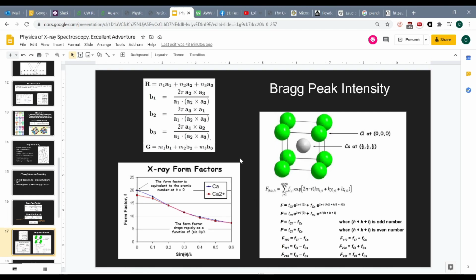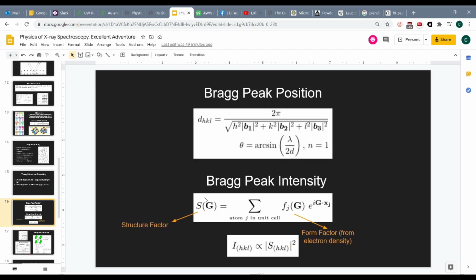Okay, so a little bit more about the Bragg peak intensity. The X-ray form factor can be calculated either experimentally, or you can do some rather involved derivations involving the electron density, and you can get very into it. But it drops off rapidly as the sine of theta over wavelength increases. So that's going to lead to a phenomenon where overall our peaks are going to be smaller at higher angles because the form factor has decreased. Okay. So we know that the structure factor is given by this equation.